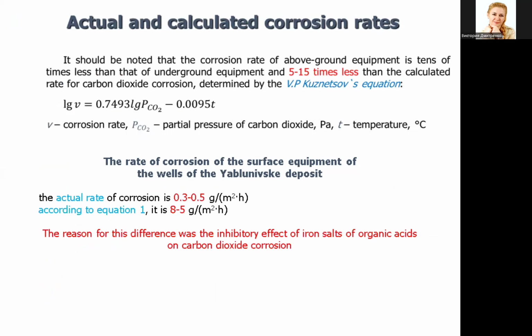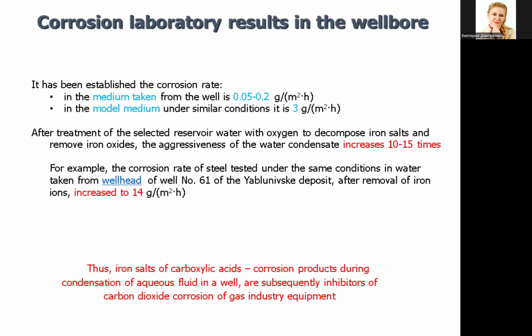It should be noted that the corrosion rate of above-ground equipment is tens of times less than that of underground equipment and 5-15 times less than the calculated rate for carbon dioxide corrosion determined by Kuznetsov's equations. The slide shows the calculated and actual rate of steel corrosion at the Yablonivsky deposit. The reason for this difference was the inhibitory effects of iron salts of organic acids on carbon dioxide corrosion. This assumption has been confirmed by laboratory studies. It has been established that the corrosion rate in the medium taken from the well is 15–60 times less than in the model medium under similar conditions.